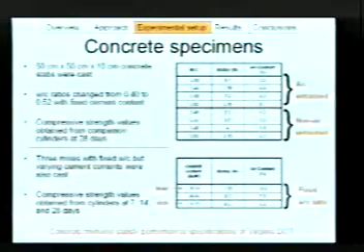So what were these slabs? We decided to make several concrete specimens that were 50 centimeters by 50 centimeters by 10 centimeters thick. These slabs were to mock pavement, and that's why we decided to change several parameters. First, we decided to vary the water-cement ratio from 0.4 to 0.52, as you can see over there in the table. We also considered that adding an air entrainer was important because this work is partially funded by the Virginia DOT, and they are usually worried about the use of air entrainment because of the changes in weather.